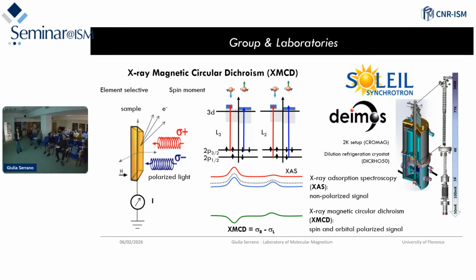So the difference between these 2 XAS signals corresponding to the two polarizations gives rise to this XMCD signal, this dichroic signal, which is proportional to and gives a fingerprint of the magnetism of the sample. And for us this is a really important tool.